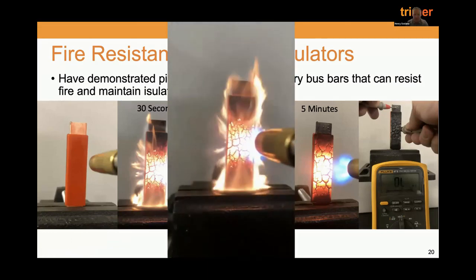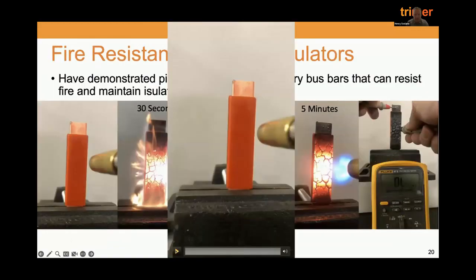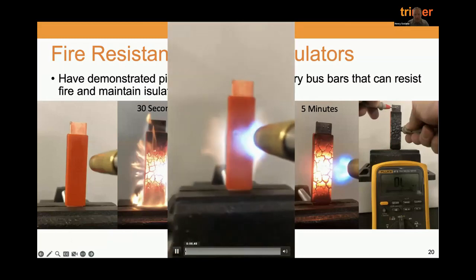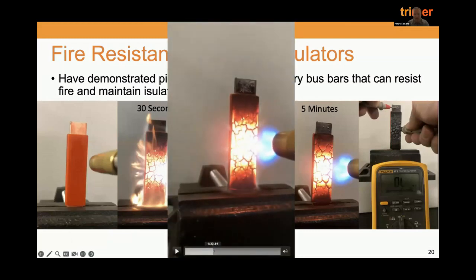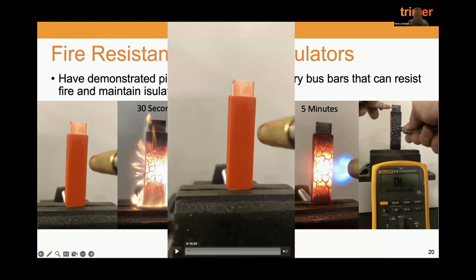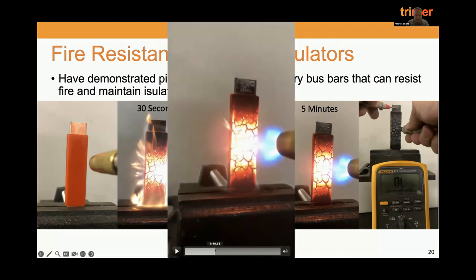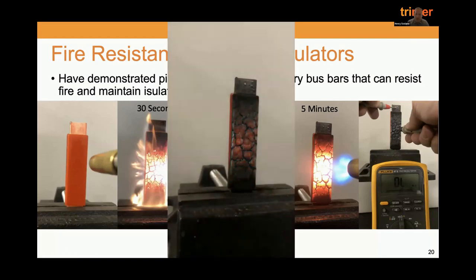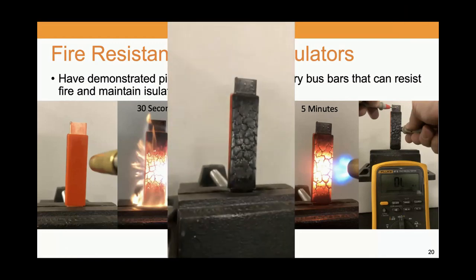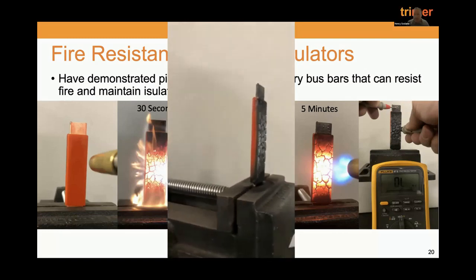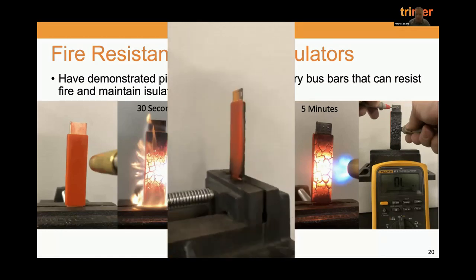Hopefully the volume isn't too loud on that for everybody. This is a blowtorch that's being applied to this. It goes for 5 minutes, and I will just pull this along. It's basically inert. If you look at the flame on this, it's very intense. So what's happening here is, again, this is about 4 minutes and nothing is happening. This is neat resin. There's no reinforcement, so it does fissure because it does have some pyrolysis and volume change. And I'm going to stop it about here, and I will spin this part around, and you'll see it immediately flamed out. There's no residual. And on the back side of this, you see that it's not even discolored. So that's the thermal stability of the material, really high performance.